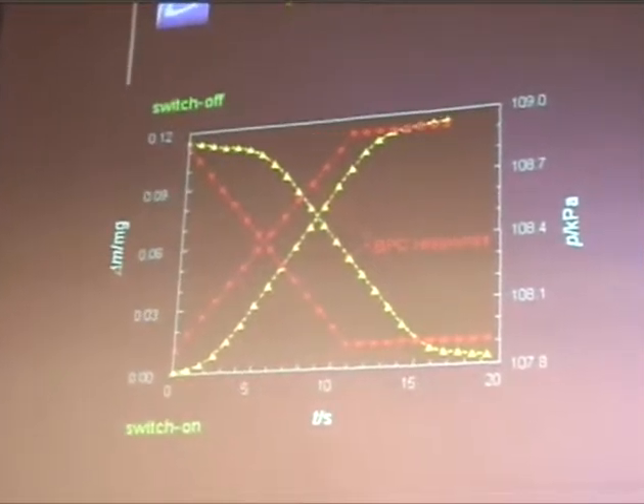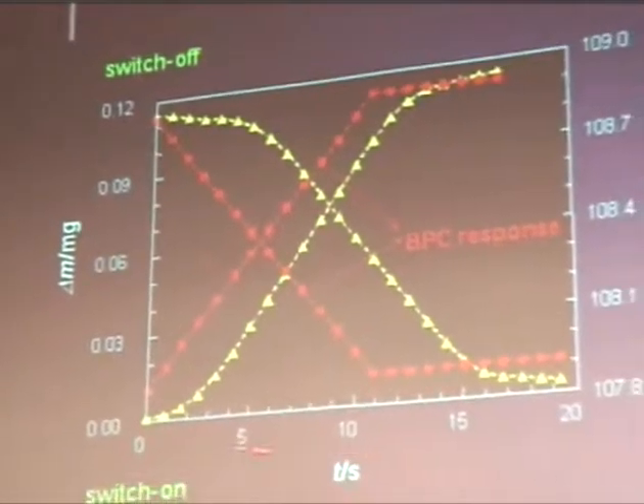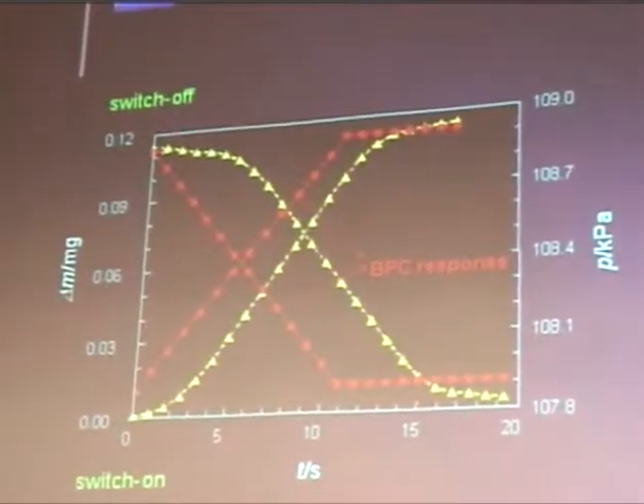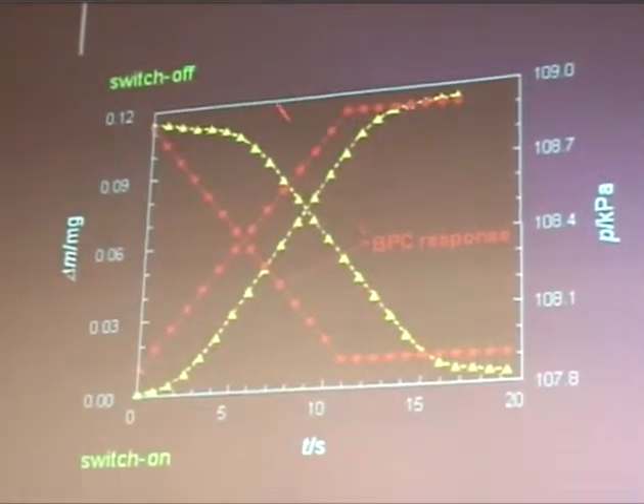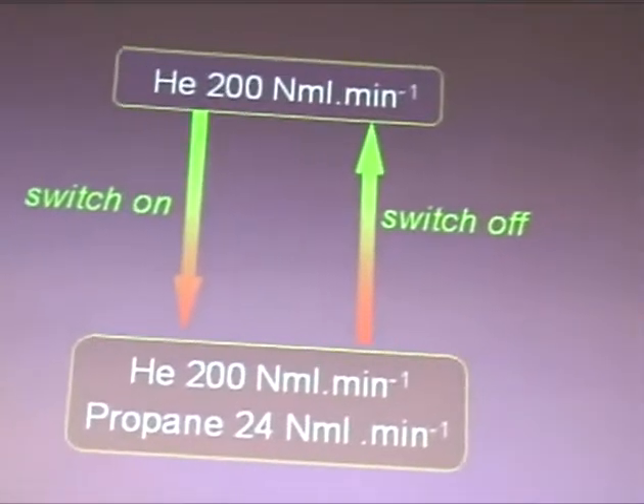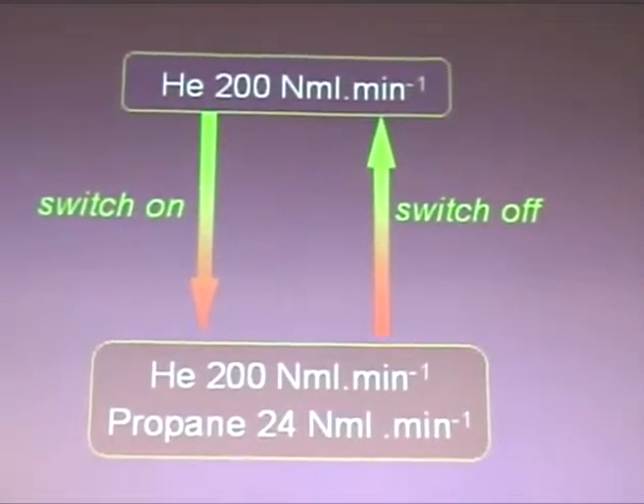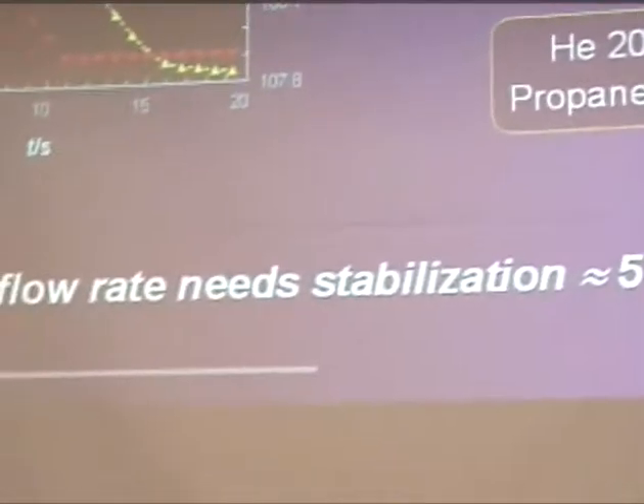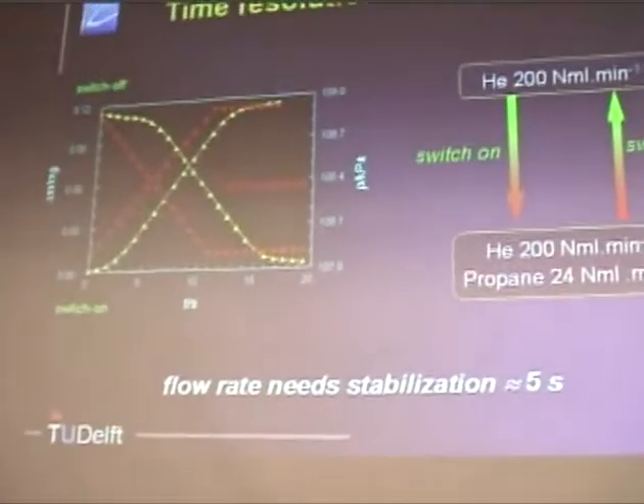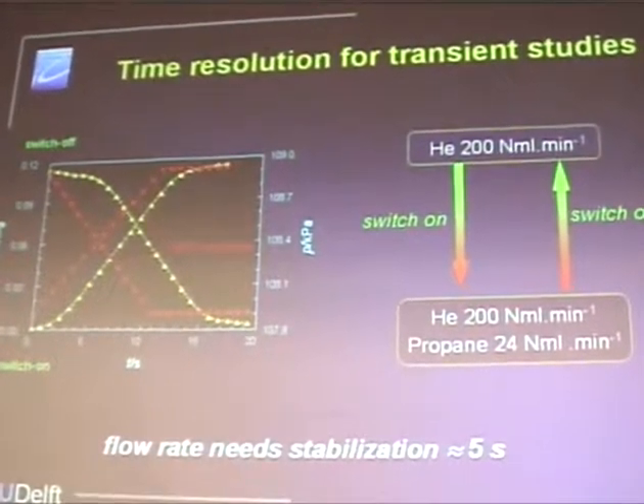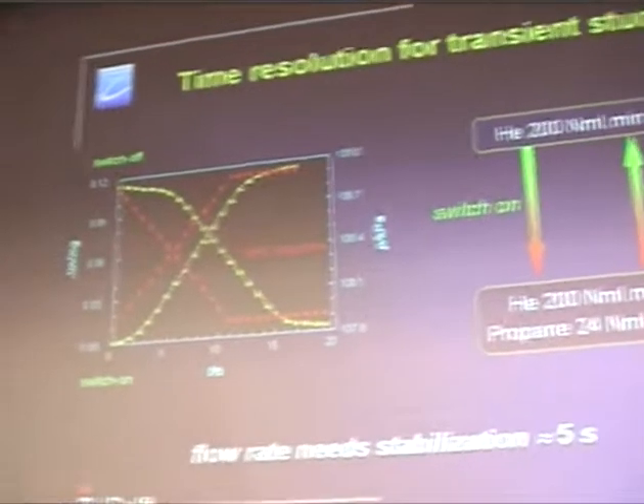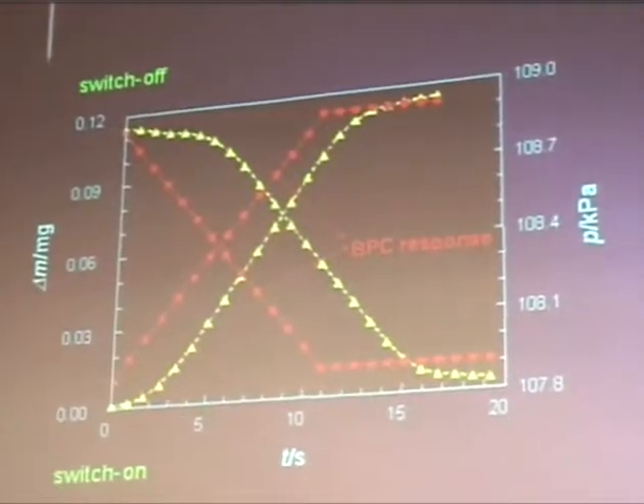Here's this example of our instrument. You want to know how good the sensing conditions are, and here when we change the pressure, the time marks are 10 seconds, you see that the TEOM lags behind a little bit, about 5 seconds. That's because of our flow equipment, so our flow is the limiting factor. The microbalance itself has a sensitivity of about 0.1 second. So we work where we can accept 5 seconds, which is already very good.